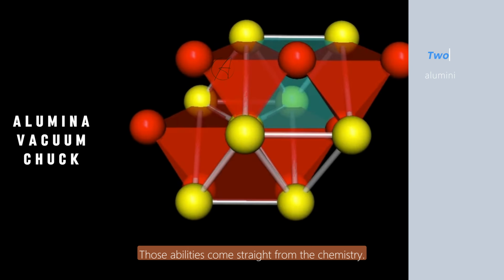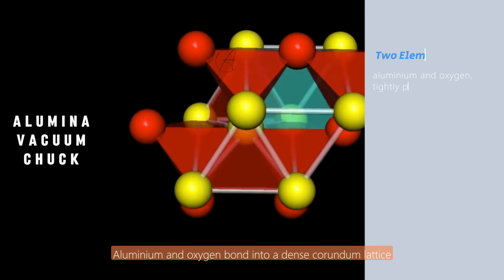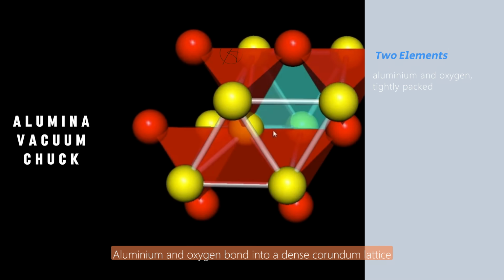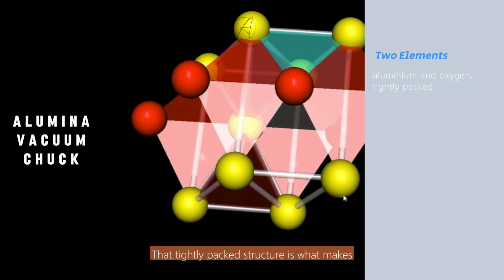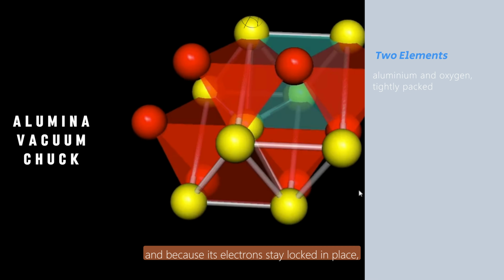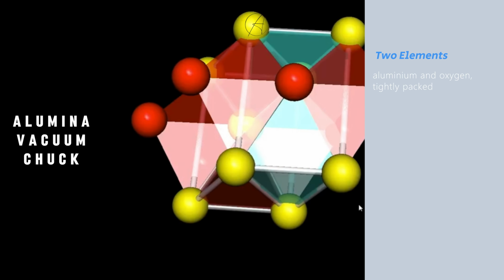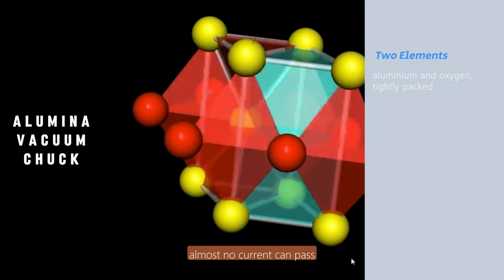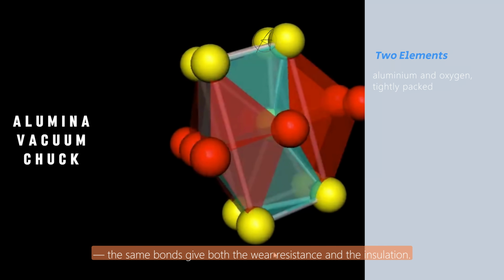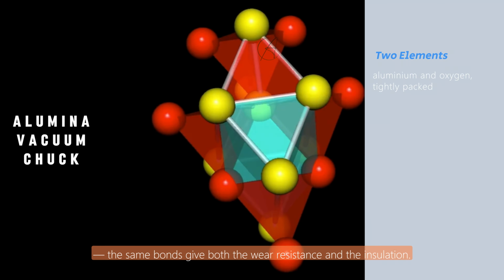Those abilities come straight from the chemistry. Aluminum and oxygen bond into a dense corundum lattice held by strong ionic and covalent links. That tightly packed structure is what makes alumina so hard and so stable, and because its electrons stay locked in place, almost no current can pass. The same bonds give both the wear resistance and the insulation.